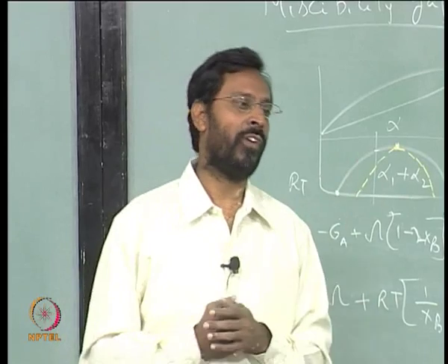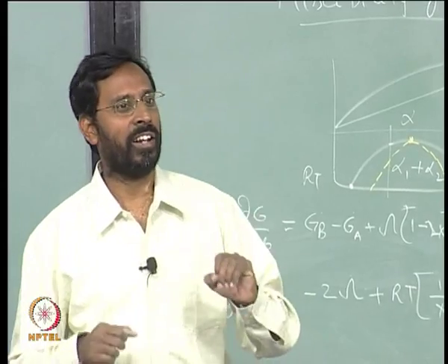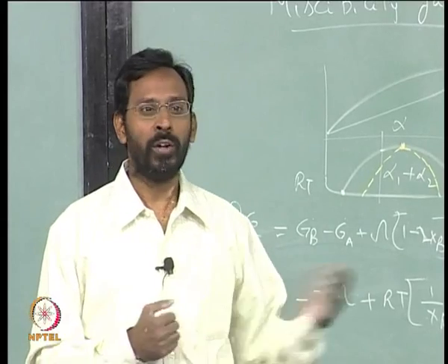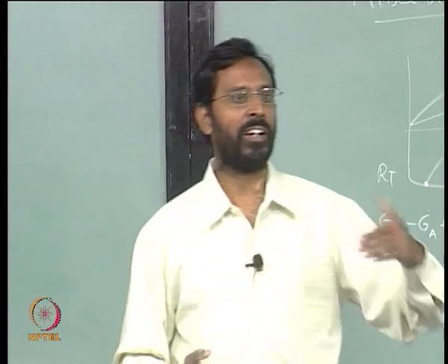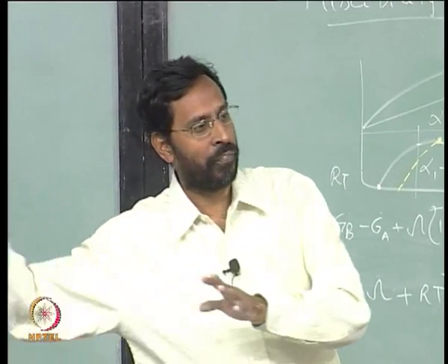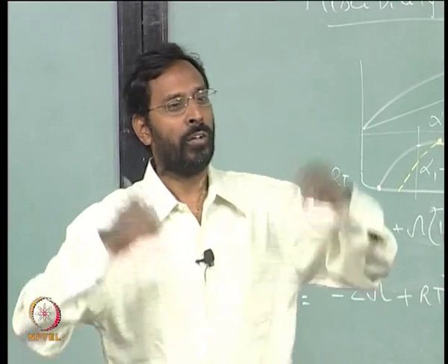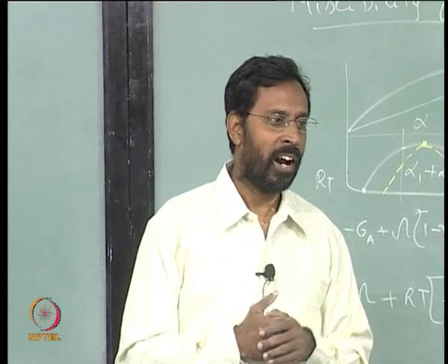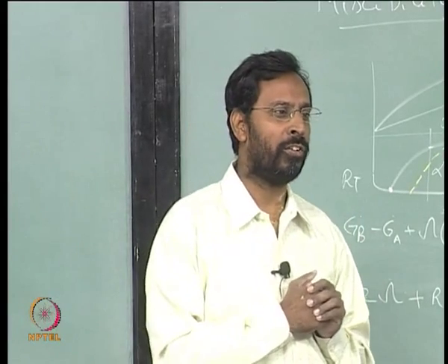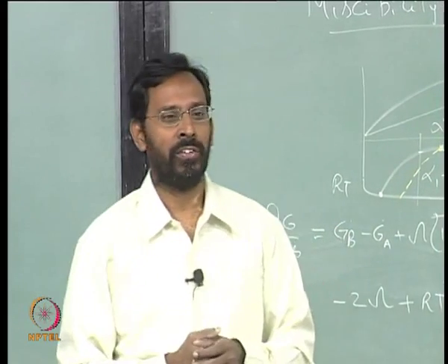Second is look at size factors again. We know that you would get a glass whenever the size factor is greater than a certain number, so that solid solution is not preferred. We know from Hume-Rothery that when the size factor is less than something you get a solid solution. So all those conditions which would prefer a solid solution formation would lead you to a high entropy alloy without being amorphous, and all those conditions which are not conducive for a solid solution formation are the ones which would lead you to a glass provided you have a multi component system.